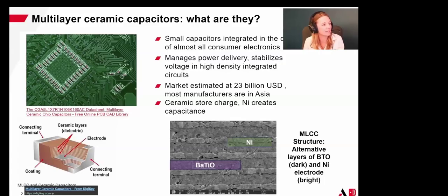These tiny rectangles, if we cross-section and cut one in half, what we'll see are interleaved layers of ceramic dielectrics and metal electrode materials. So here's an SEM image of one that was cross-sectioned or cut in half. These bright areas in this case are nickel electrodes, and these darker regions are a barium titanate based ceramic. And we'll talk a little bit more about why barium titanate is used in the coming slides.